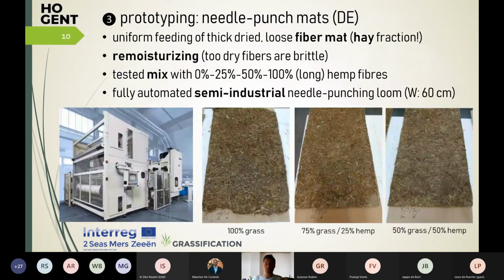With this material, we performed an outdoor test during 3 months to test the cohesion and the functionality in a weed control experiment, comparing it to commercial alternatives.